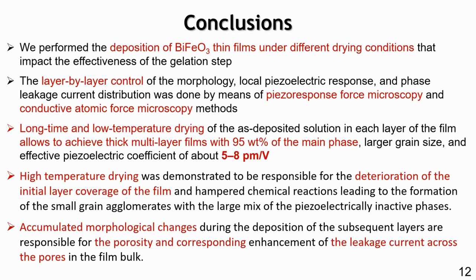And the combination of the PFM and conductive AFM methods allows us to inspect it very, very carefully. And we found that the long time and low temperature drying procedure is very important to create a perfect material with a high piezoelectric coefficient, which is in line with the piezoelectric coefficients of many ferroelectric single crystalline materials. But high temperature drying is really not the best solution for creating perfect, high quality films. From the physical point of view, we can say that during layer-by-layer deposition, we have accumulated morphological changes. These accumulated morphological changes cannot be seen at the final stage when you check the morphology of the final thick film. But they can significantly impact the leakage current and the porosity of the final structure.